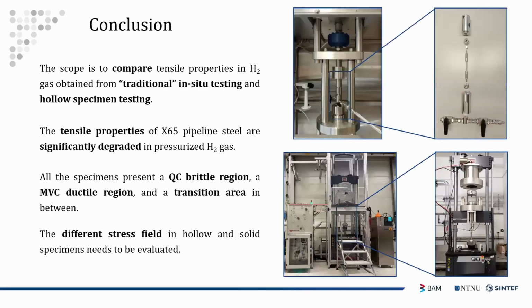So in order to summarize the main results of this research, the scope of the overall study was to compare the tensile properties in high-pressure hydrogen environments obtained with a traditional in situ testing technique, so using the autoclave, and the more novel hollow specimen testing technique. And for all these tests, we figured out that the tensile properties of vintage X65 pipeline steel with banded ferritic and pearlitic microstructure are significantly degraded by pressurized hydrogen gas. So the existing Norwegian pipeline network could be repurposed for hydrogen transport, but with lower pressures for sure, so lowering the operating pressure of the pipelines.